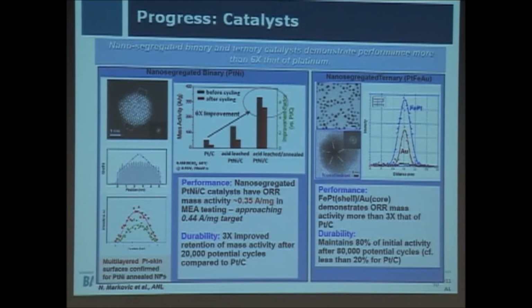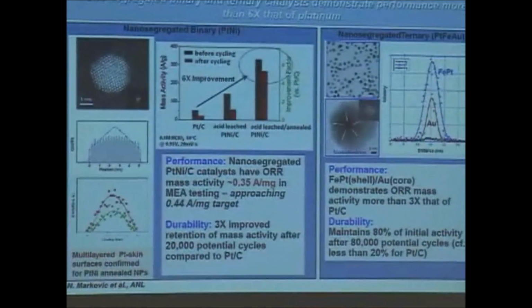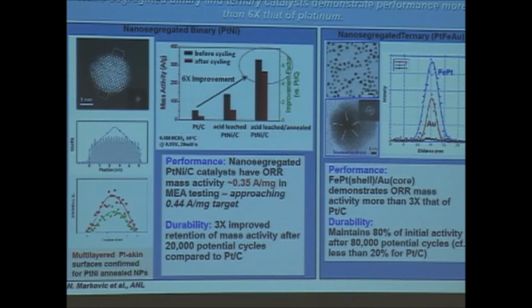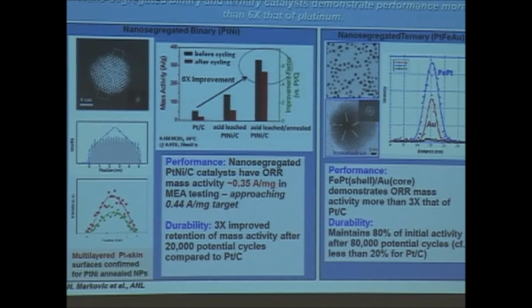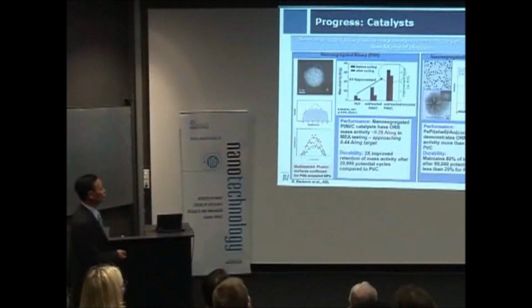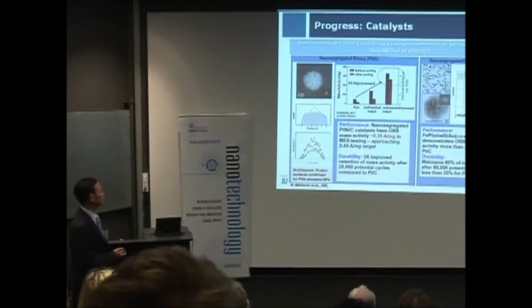The good thing is that in the last couple of years, we did make great progress on catalyst performance and durability improvement. This is one example from Argonne National Lab. They use a nanosegregated binary catalyst. They claim to have a 6 times activity improvement compared with platinum. Particularly if they combine it with iron and gold as a ternary catalyst, they also have an opportunity to improve not only the activity, but also the durability.